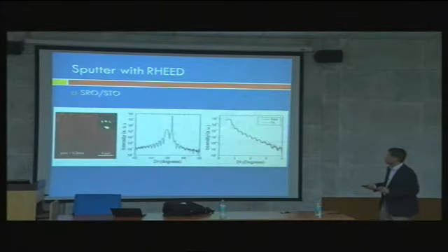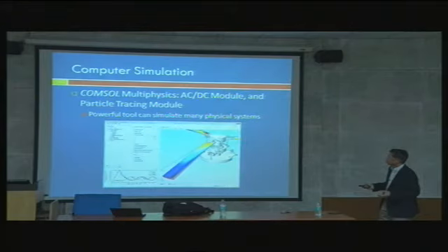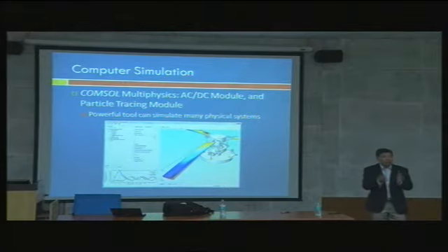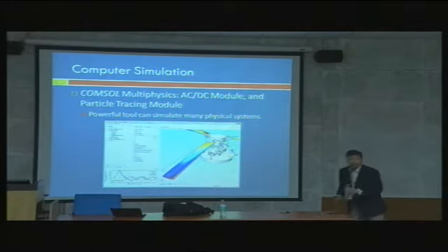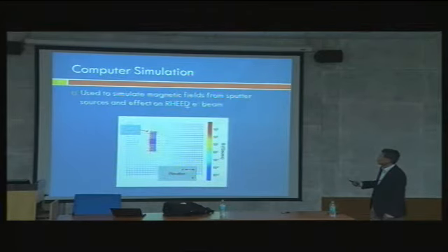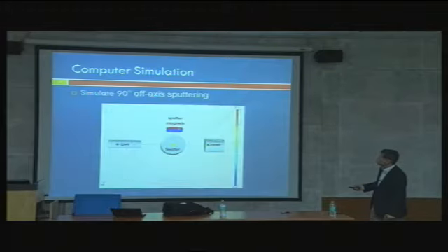Okay. So I think the surface roughness and the thickness oscillation of the sputtered film are as good as PLD. But one thing we use is computer simulation, which allows you to design your chamber to minimize the magnetic field effect. So we use the simulated magnetic field pattern, and when you use a single target, like this off-axis sputtering, with one target, the electron beam actually bends this much.